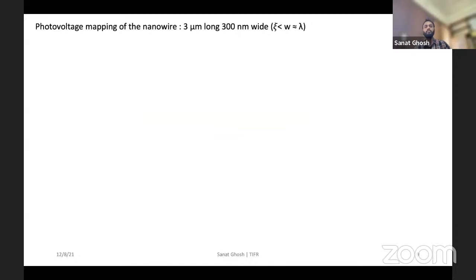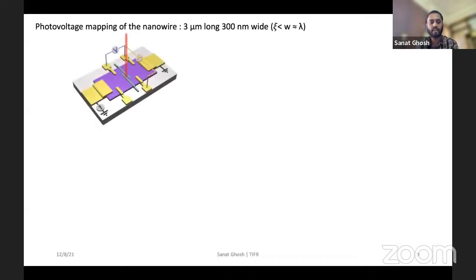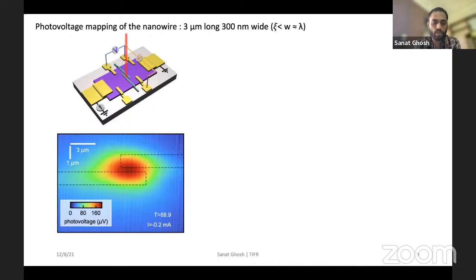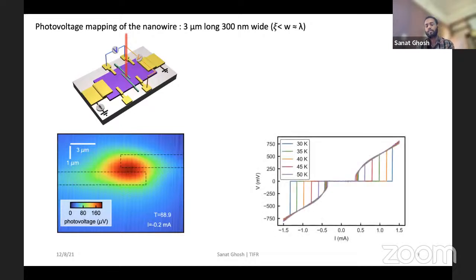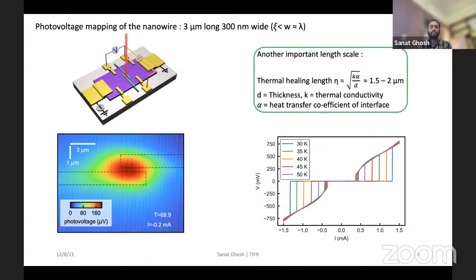Next, we make another superconducting nanowire of 3 micron length and 300 nanometer width. In that case, we found that there is only one photovoltage spot along the nanowire, and there is no resistive transition from superconducting to normal state, as we see for a longer nanowire. The reason why we don't see these multiple phase slip events here is not very clear to us for now.